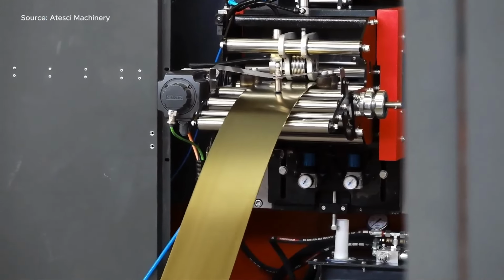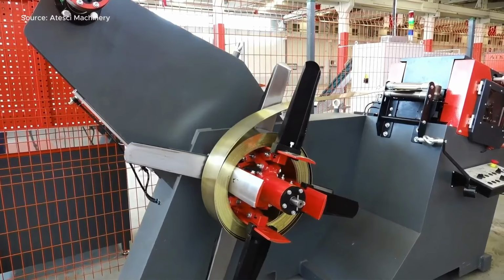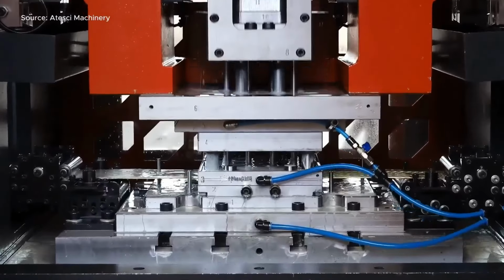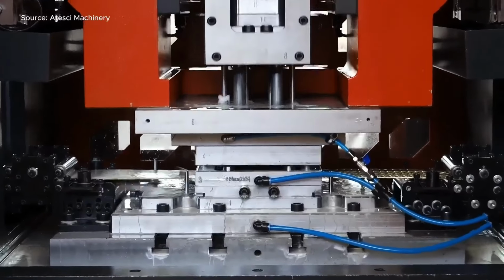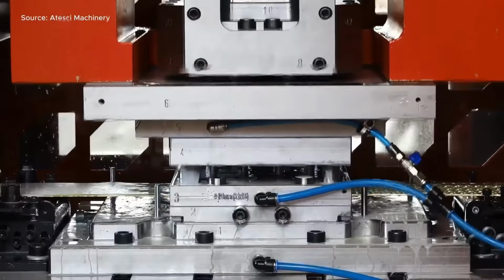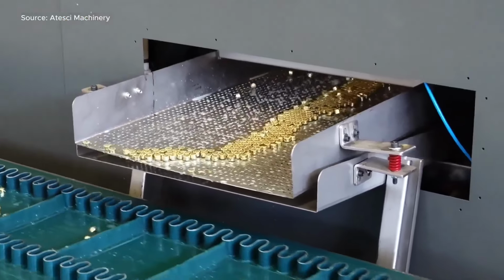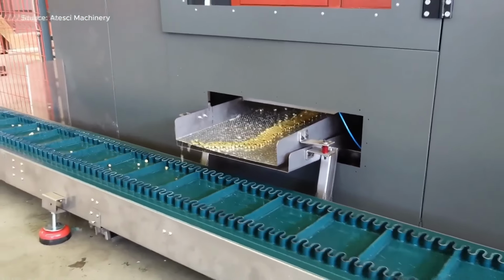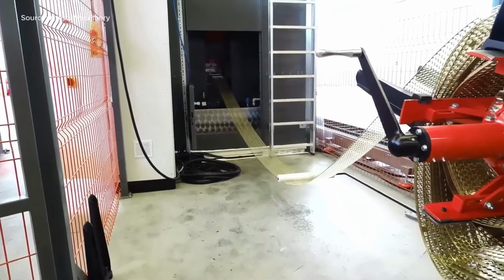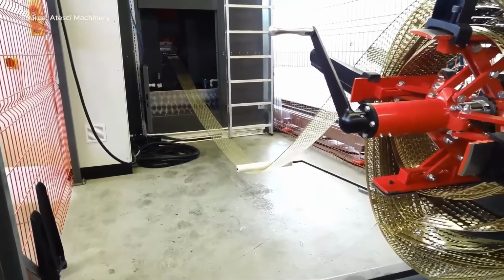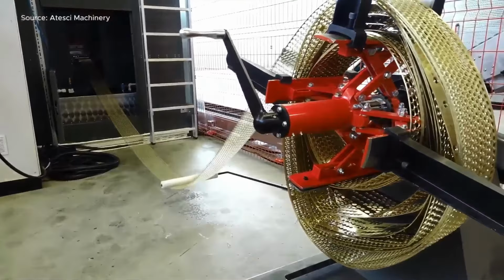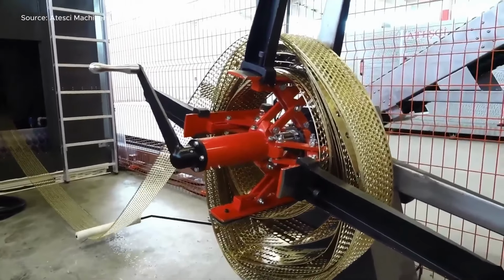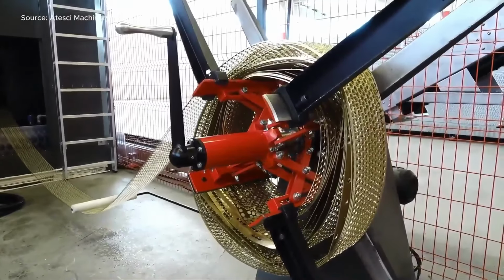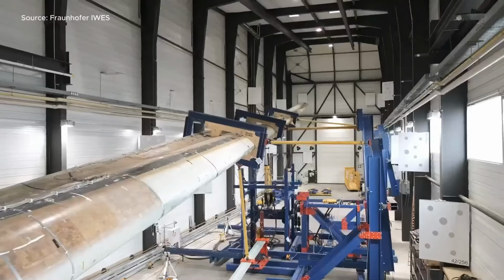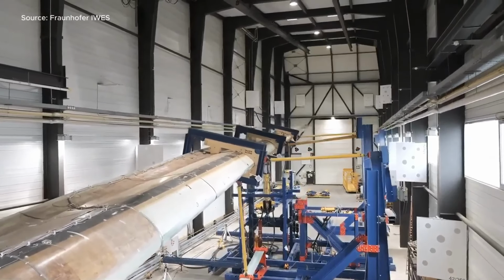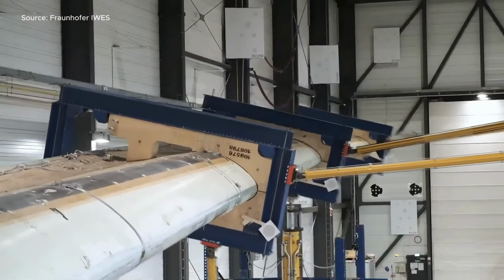Atesci's blanking and cupping press efficiently processes metal strips into cups. It operates at 80 strokes per minute, with a 100-ton capacity, and requires a 20 kilowatts power supply. The machine's size is 2,350 millimeters W, 2,800 millimeters D, and 3,870 millimeters H, with a total weight of 13,500 kilograms.